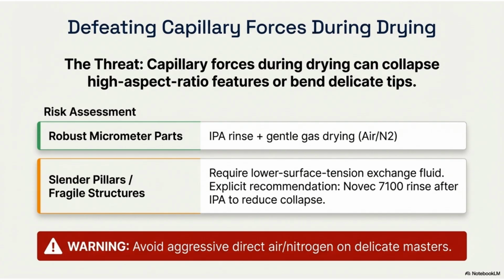Capillary forces during drying pose a threat, capable of collapsing high aspect ratio features. Robust parts can use an IPA rinse and gentle gas drying. Slender or fragile structures require a lower surface tension exchange fluid, such as a Novec 7100 rinse after IPA to reduce collapse. Avoid aggressive air or nitrogen on delicate structures.